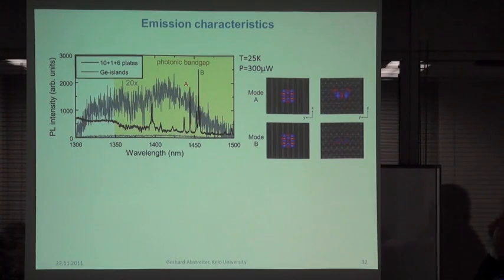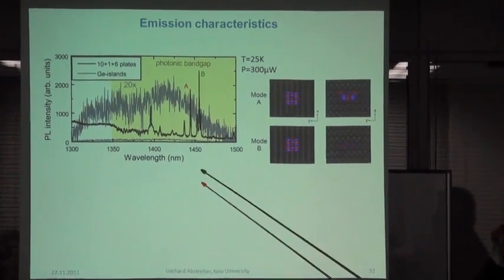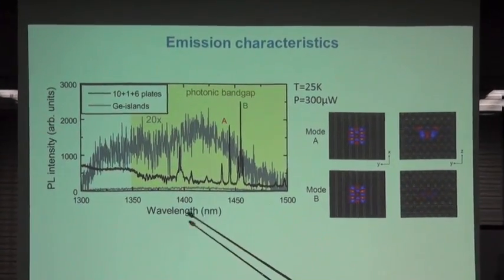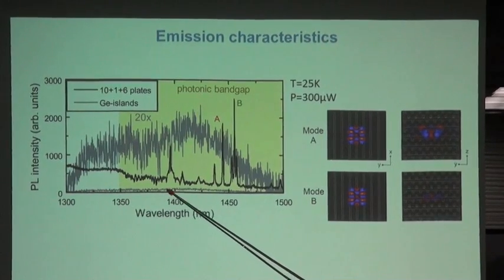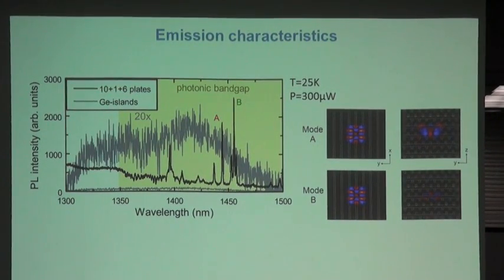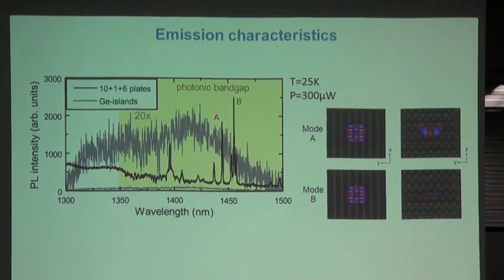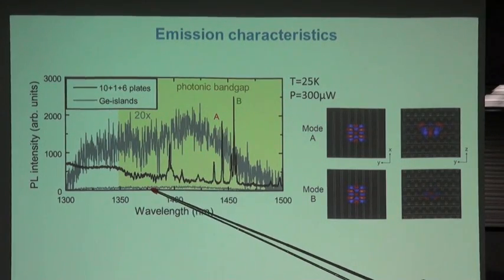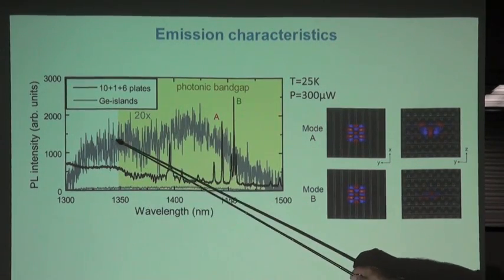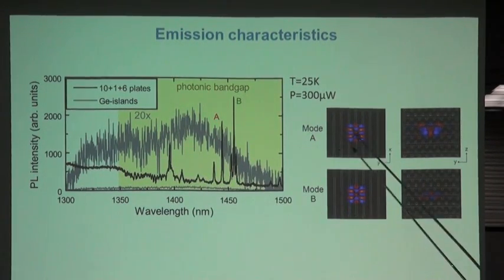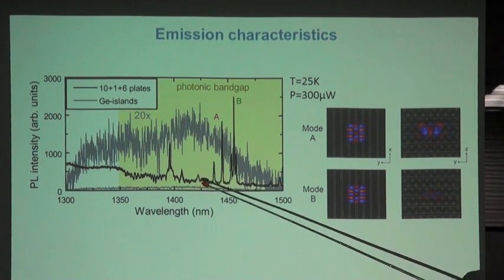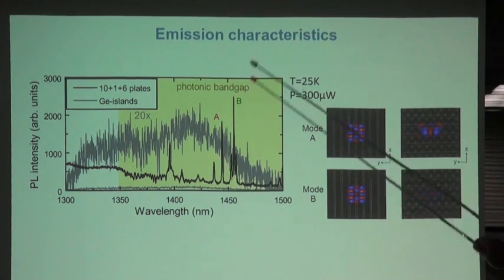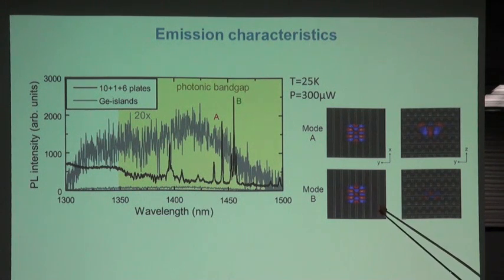Now, when you look at the spectrum of the germanium islands, this is again the germanium islands of this one thin plate outside. And I expanded this here by a factor of 20. And now you measure on this photonic crystal, you see immediately that you get, again, these very sharp lines, which are modes in the system.